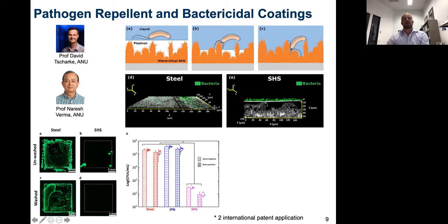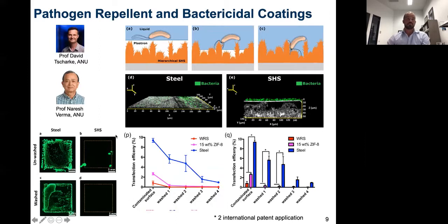But what we were thinking about is, well, what happens then if we submerge it for extended periods of time, or if those surfaces are not pristine and they're damaged, and the bacteria can then start to colonize these surfaces. So what we did is we actually imparted some metal organic frameworks in there. So we have a bactericidal aspect to the coating, and we can show that we can actually submerge these for over 9 days and they can sustain significant damage, and they're completely resistant to bacteria.